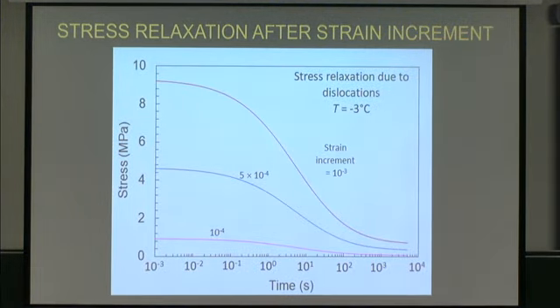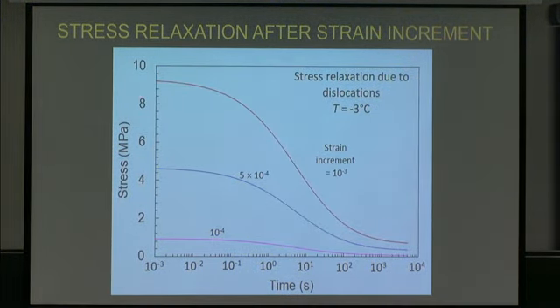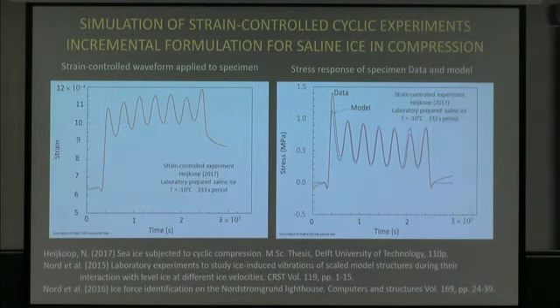That being said, you can see how each of those behave. Here's how the model would behave with 3 different increments in strain. And so you hold that strain, and the stress would relax according to these type curves in a matter of seconds or minutes. So this next simulation basically is employing that method of calculation.